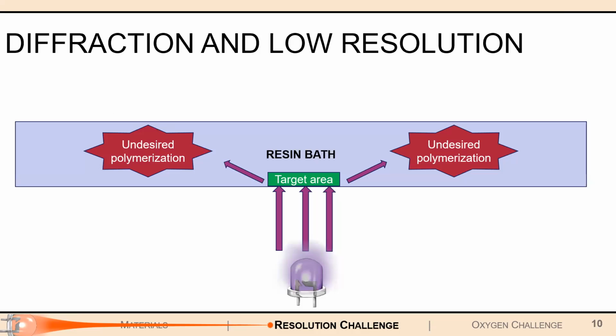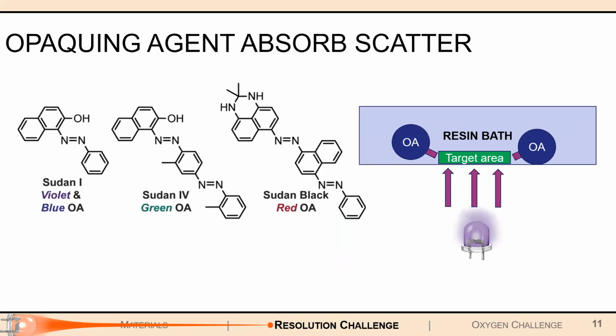Essentially, that pattern light will hit the target area and create the desired polymer layer, but then some of those photons will scatter and diffract through the resin and trigger undesired polymerization elsewhere in the system. That is the reason why we get this lower resolution and the blobbiness that you saw in the previous photo. The solution that we found was to use a type of compound known as an opaquing agent. These opaquing agents absorb certain wavelengths of light and prevent it from diffracting through, as you can see in the figure to the right. That essentially keeps the pattern light in that region and allows for sharper resolutions.